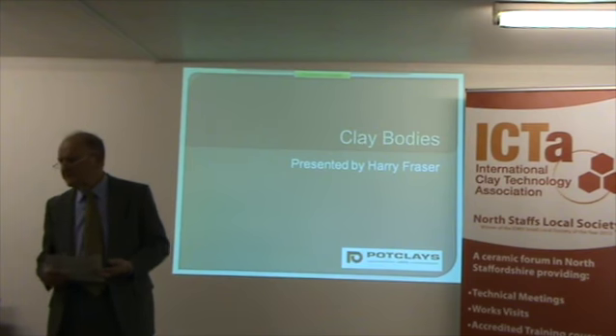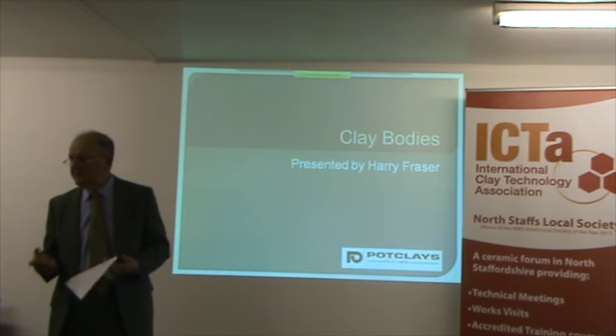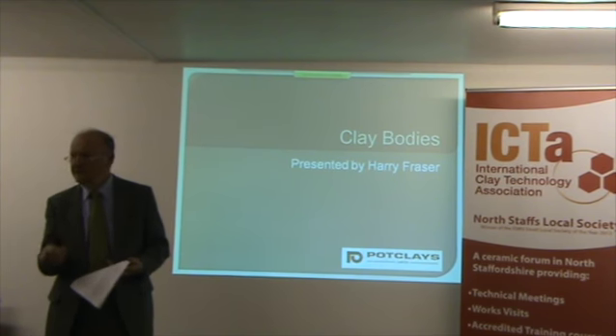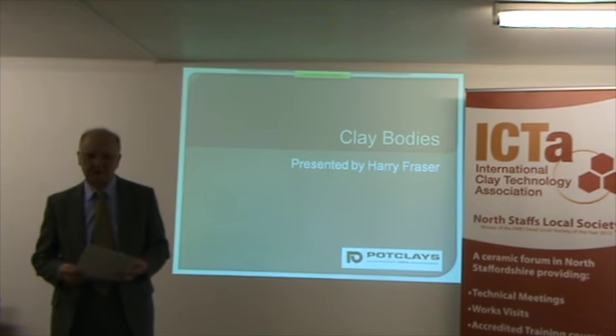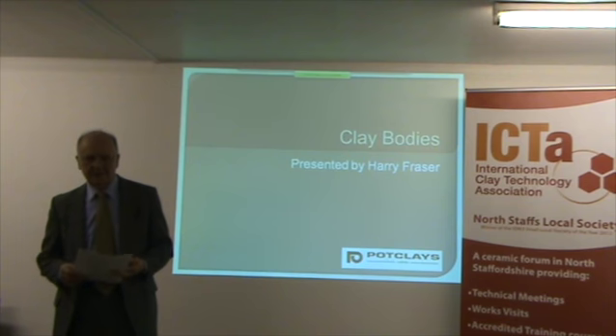We can measure things that are related to plasticity. We can measure the green strength, the tensile strength of clay bars, for example, using a modulus of rupture machine, and compare the strength of one clay with that of another. Because we know that the more plastic the clay is, almost always, the greater the dry strength. And of course, we can also measure the shrinkage. The more plastic a clay is, the more it'll shrink upon drying. So we can measure these things, but it's not really an accurate indication of plasticity, because it only measures some of the factors which make things plastic.